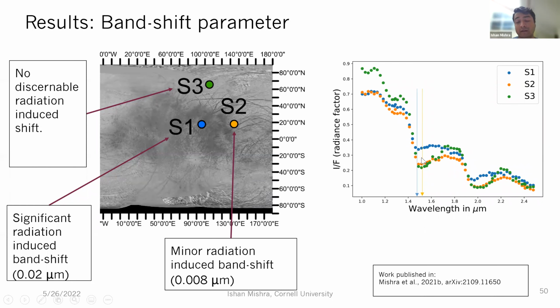Previously, to get around this problem, people would just discard the data that is coming from the water ice band. But instead of discarding the precious data, what we decided to do was have an empirical parameter that shifted the water ice band, so that you don't need to change your abundance to force fit that shift. And this is the result for that parameter. We got the most amount of shift for S1, as you can clearly see, and that is what you would expect. And S2 and S3 pretty much showed no shift. When I'm talking about shift, I mean as compared to a neutral water ice spectrum. So S1 is the most shifted because it's the most irradiated. So it works well with our expectation.